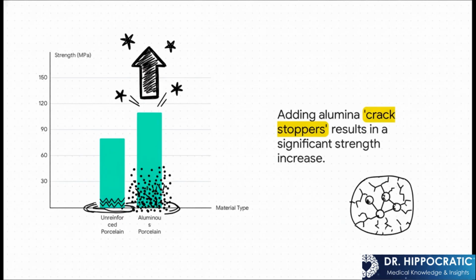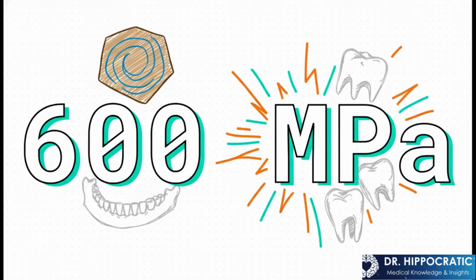Its flexural strength is about 80 megapascals, or MPa. Now watch what happens when we just add those alumina crack stoppers. Boom. The strength jumps up to over 110 MPa. That's a really nice improvement for sure, but we're just getting warmed up. Now you might want to sit down for this.